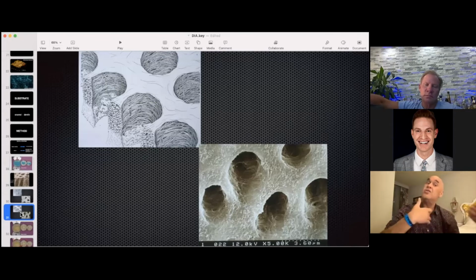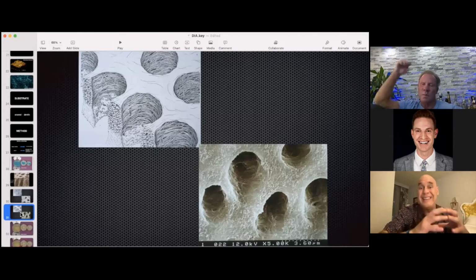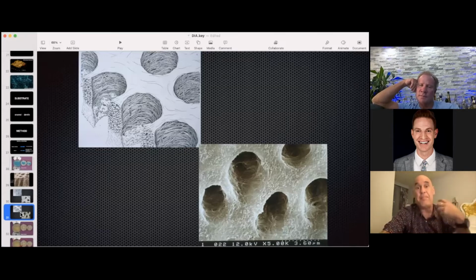So now, because you etch the dentin with phosphoric acid and you expose the dentinal tubules, now you need to make sure that you manage your dentin properly so your adhesive can penetrate through the collagen and then seal your dentinal tubules. If you are not capable of doing that, you are going to experience sensitivity related to bonding, which is different than the sensitivity that can be related to occlusion, other things. But when it comes to bonding, this is it.